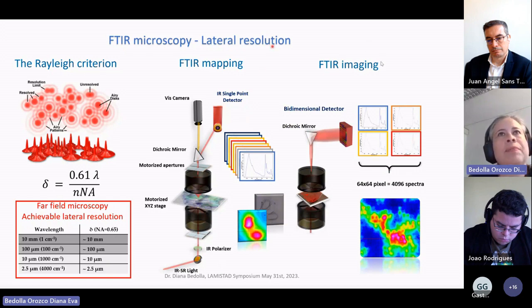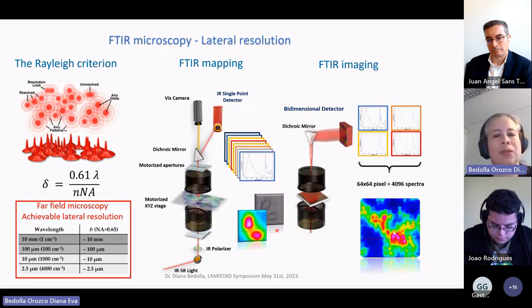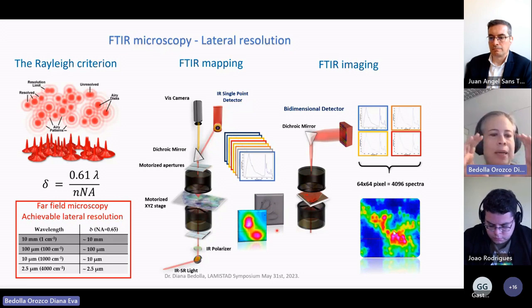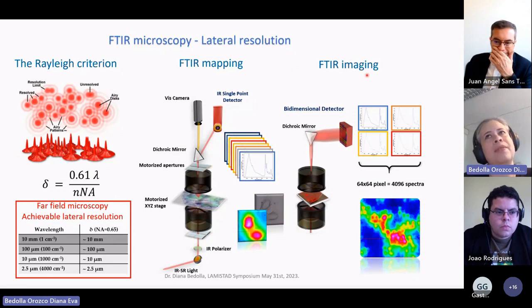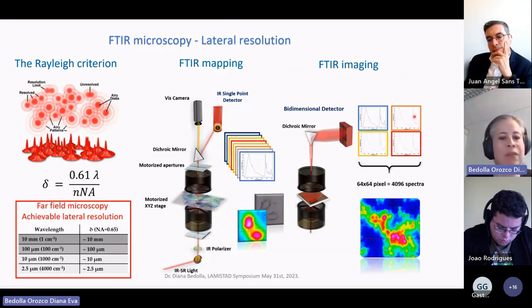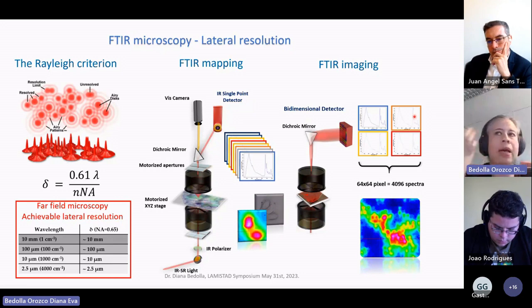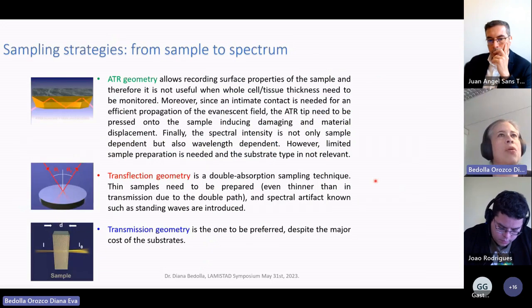So there are two ways of acquiring a spectrum of an area. One is by mapping, and in that case, you're concentrating the light into a single point and then moving your stage further and building up the matrix. And the other one is FTIR imaging, in which you actually have a focal plane array, which is an array of single detectors. They're all coupled together. And you can get in one shot 4096 spectra in this case, because we have a 64 by 64 pixel array. So we can also sample in different ways.